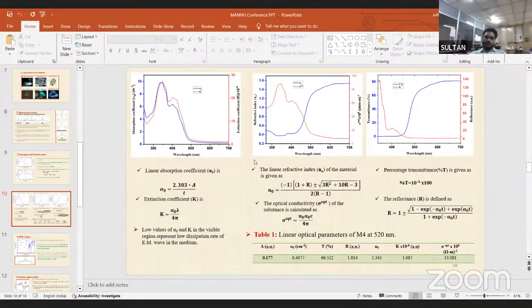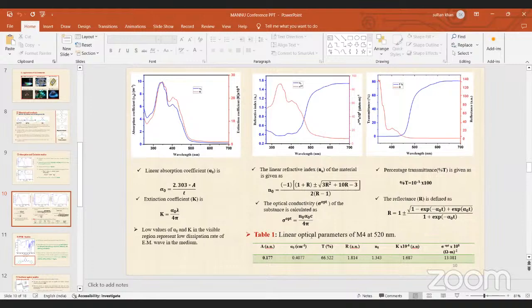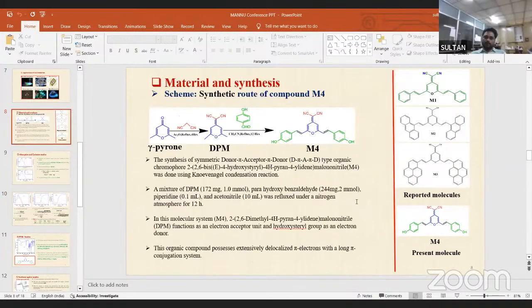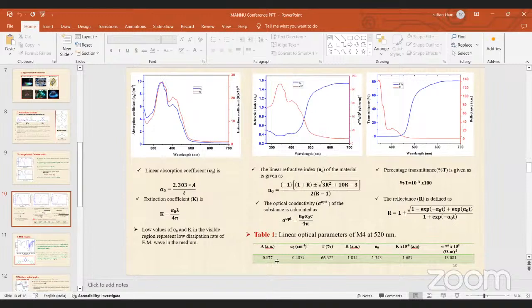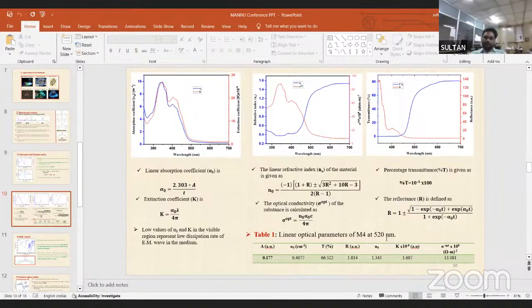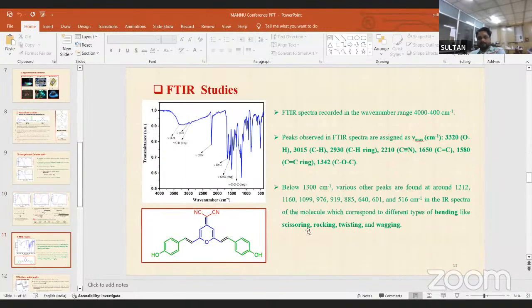We have calculated the linear absorption coefficient and extinction coefficient, and also refractive index, optical conductivity, percentage transmittance and reflectance using these equations. You can see all the linear optical properties depend on wavelength, and I have shown the variation of these optical properties with wavelength in this figure. I have also calculated the linear optical property at wavelength 520 nanometers, which is used in fitting and calculating the nonlinear optical property.